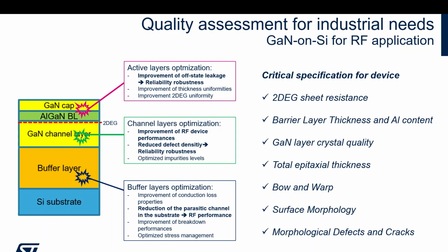Then you have the isolation channel here, and then the barrier, and then again cap on top. And you have to control the composition. Here you have another thing that you need to control, which is the composition, because in the case of AlGaN, you have a ternary alloy, in which the concentration of aluminum, the distribution and uniformity, is affecting the properties of the device. So you have also to do this.